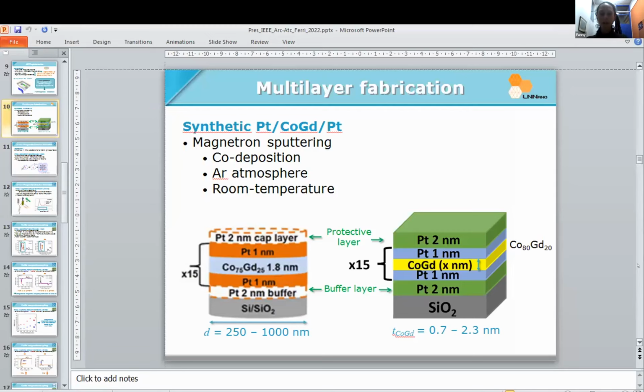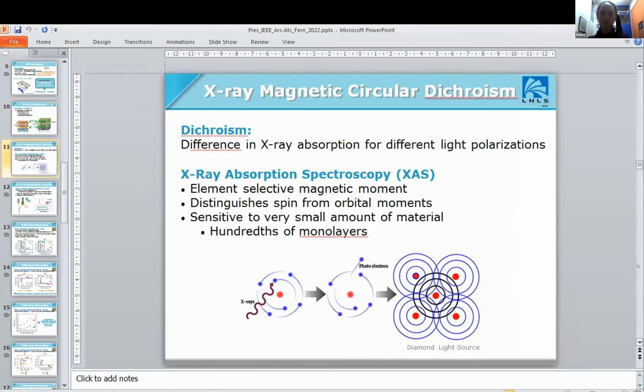So it was a two-way approach, either by lateral confinement or by varying the thickness, that we played to be able to see if we first have a ferrimagnetic alignment of the cobalt gadolinium even at these low thicknesses, and then if we were able to stabilize some skyrmions in these materials, in these systems.